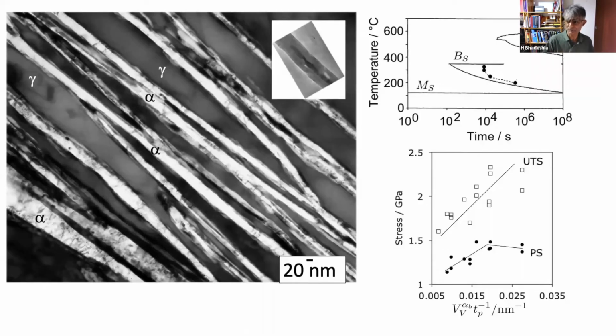Looking at a very, very small region, and these are the very fine plates of bainite. This is 20 nanometers. They are finer than a carbon nanotube, okay? Now, obviously, they are not aligned, as I showed you in the optical micrograph, but these are incredibly fine plates. And we can produce this without any rapid cooling or any deformation. This is simply a phase transformation that happens over a period of 10 days.